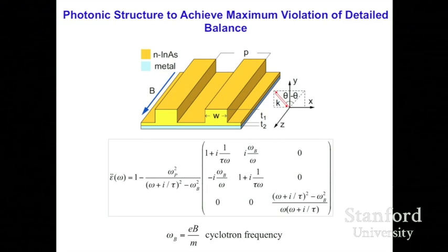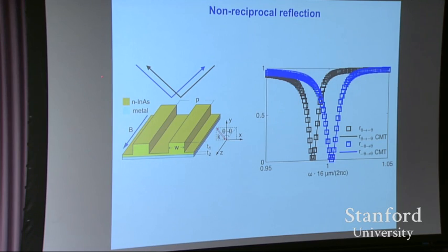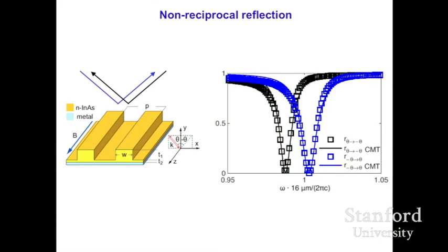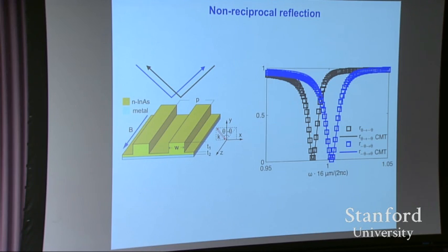So what we did as numerical work was to show that you can design photonic structures to achieve that. And the idea here is to take a low bandgap semiconductor and apply a magnetic field, and as you do that, you have a dielectric tensor that breaks reciprocity. In this case, when you look at light reflected coming from these two directions, these two directions that are related by reciprocity will have a split in the reflectivity profile.